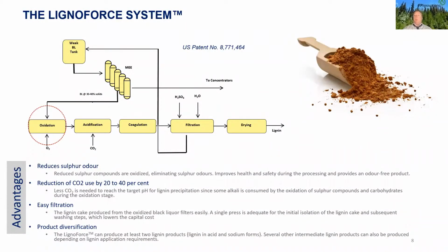On the LignoForce system approach to creating value through kraft lignin precipitation and purification, we benefit from two key steps. The first is an oxidation step, which reduces sulfur compounds and creates a much healthier work environment in the mill for producing precipitated lignin. The second is an acidification reaction, where we're able to coagulate, filter, and wash quite efficiently in a single step the lignin products, isolated in two distinct forms.